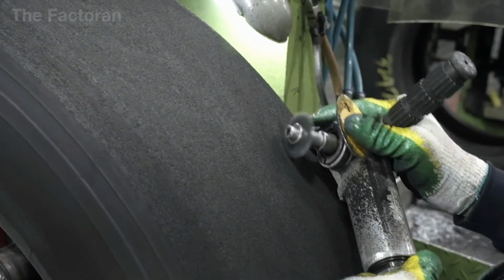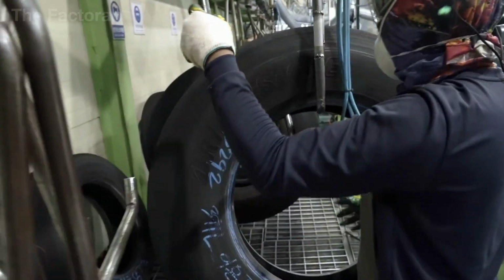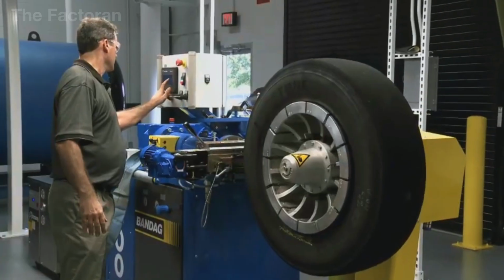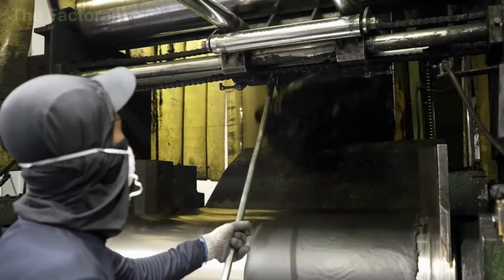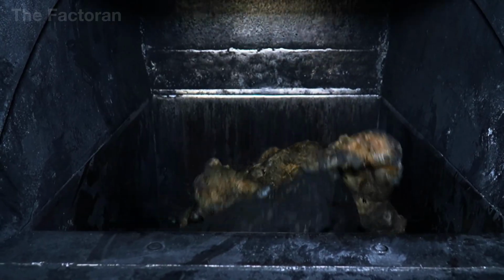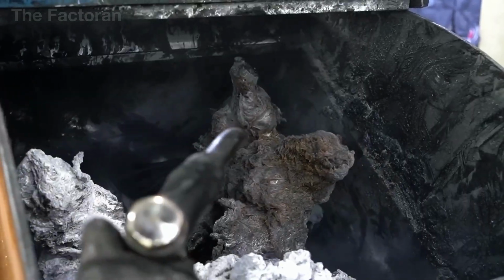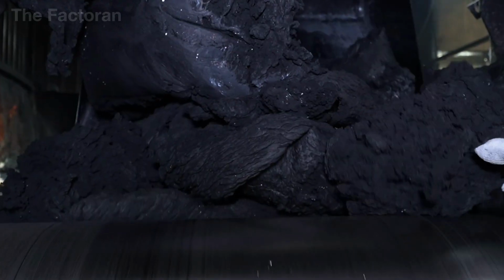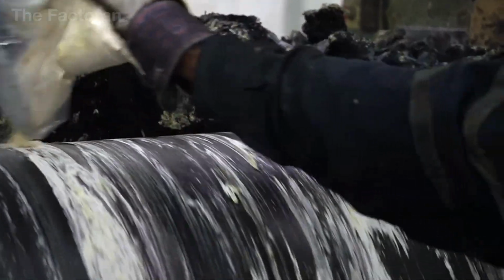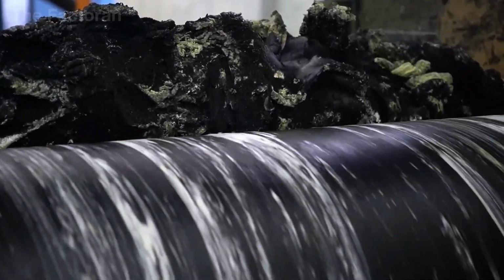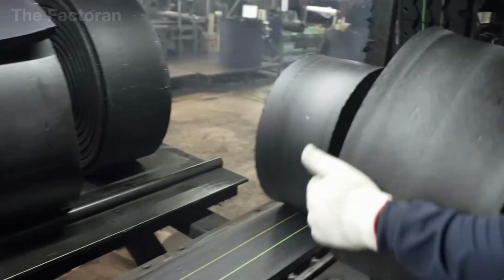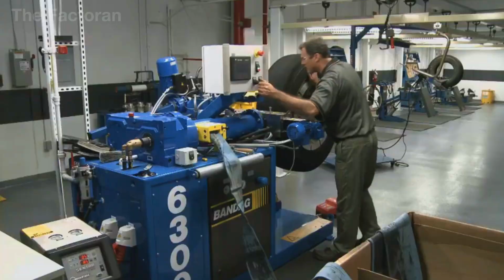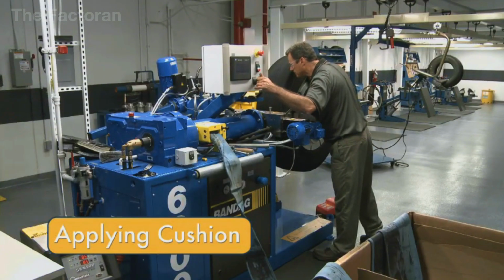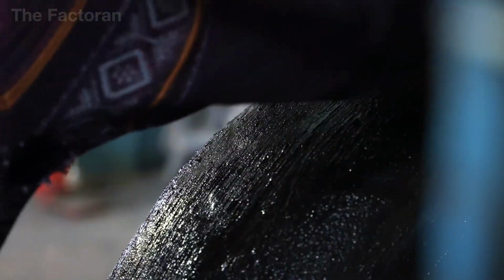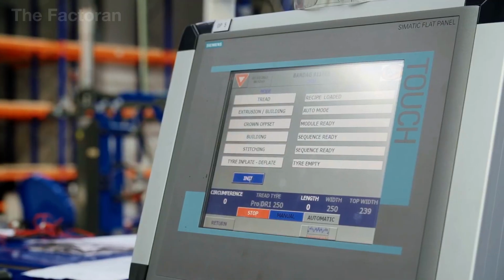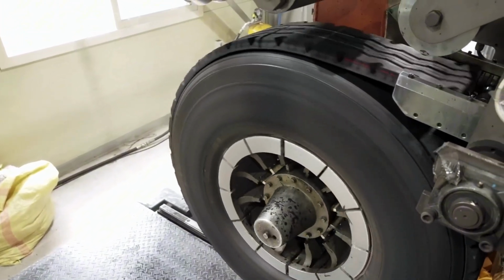After the casing has been smoothed and its flaws repaired, the tire enters the most critical stage, attaching the new tread. This is when the tire's rebirth truly begins. In the pre-cure method, tread strips are produced in advance at the factory from a mix of rubber, carbon black, and additives. These strips already carry the finished patterns and are cut to match the exact circumference of the casing. Before they are applied, workers coat the surface with a layer of cushion gum, an uncured rubber compound with strong adhesive properties. The tread strip is then pressed tightly onto the casing by a roller, ensuring an even bond with